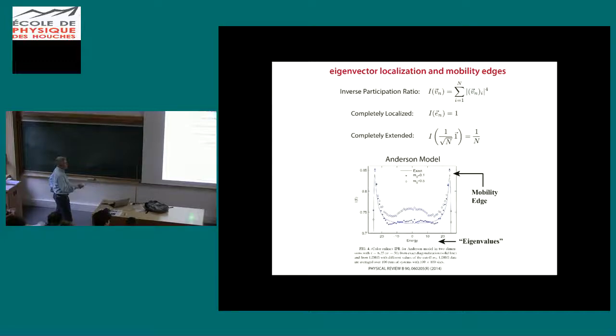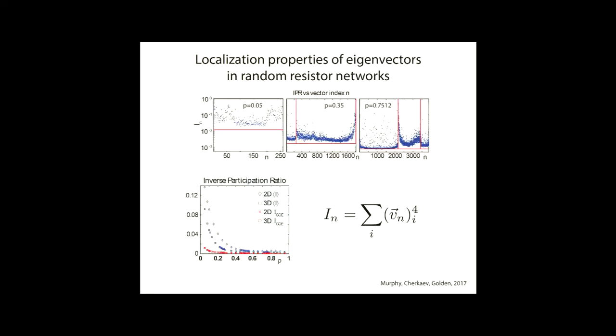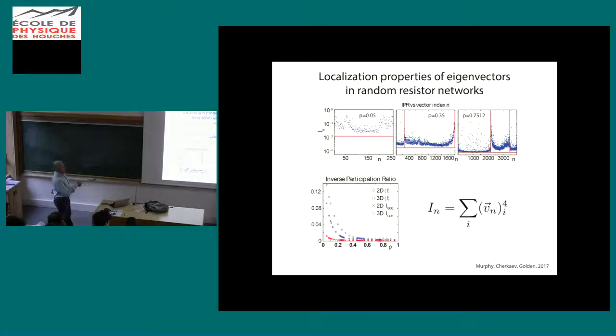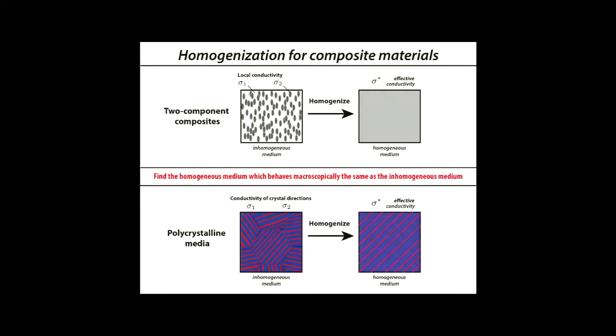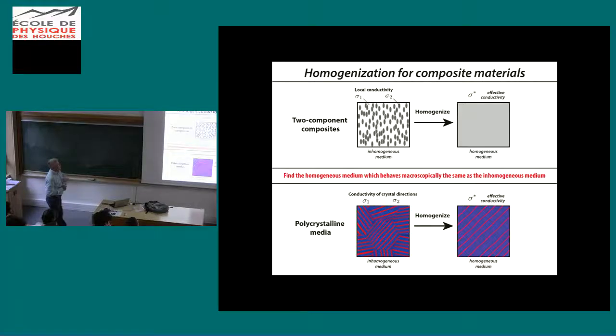Extended states are localized at these edges, and we see this same kind of behavior in the spectra for melt ponds, for the brine phase, and for these random resistor networks as well. And we see a transition to delocalization as we approach this percolation threshold. Okay, there's a whole other problem now where we can do homogenization.